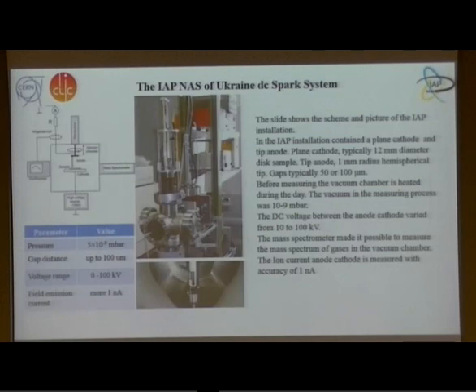The Institute of Applied Physics DC Spark system. This slide shows the schema and the picture of our installation. In our installation, the cathode is a plain electrode and the anode is a tip. The cathode is typically a 12 millimeter diameter disc sample. The tip anode has a 1 millimeter radius hemispherical tip. The gap is typically 50 or 100 micrometers.